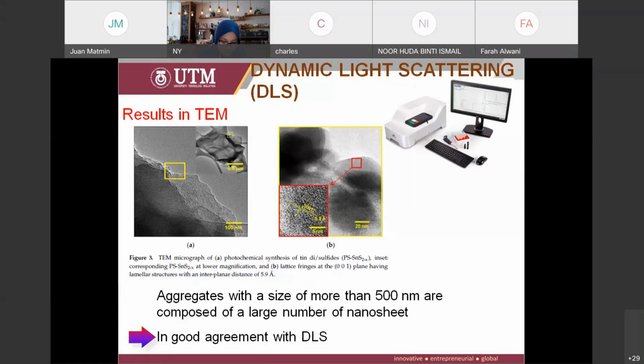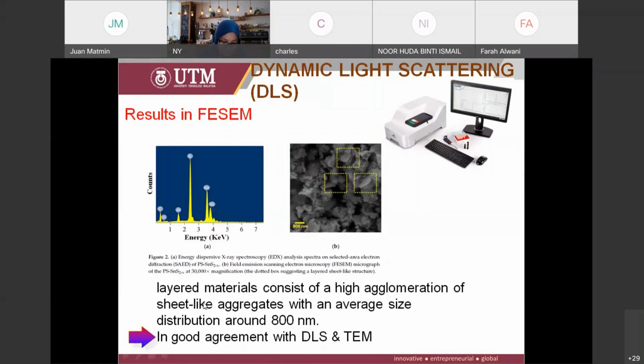So I'm happy that based on our collaboration with Sympatec Germany, we are able to publish this paper. And not only that, we also support this organization. To take a look, we have the measurement based on the DLS earlier. We support it back with the TEM, and we support with the FESEM. And this material actually consists of layered material and is highly aggregated. That's why it makes an average distribution of around 800 nanometers, which is in good agreement with the DLS and TEM.